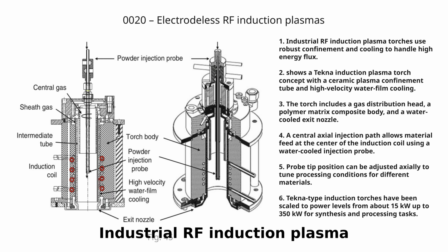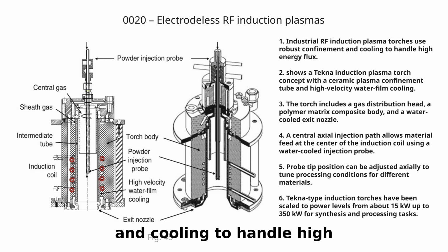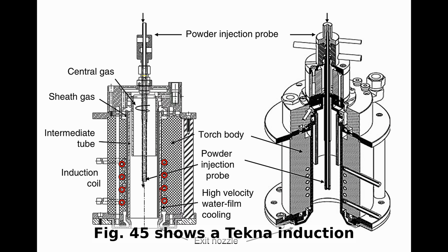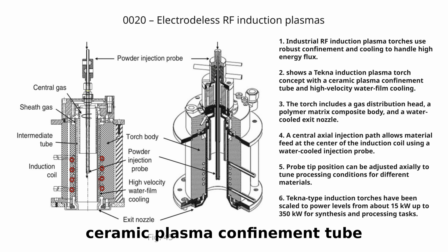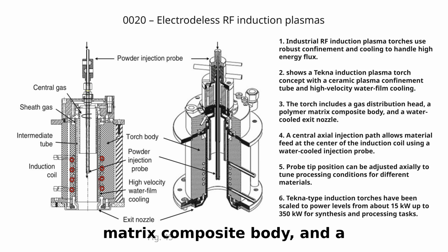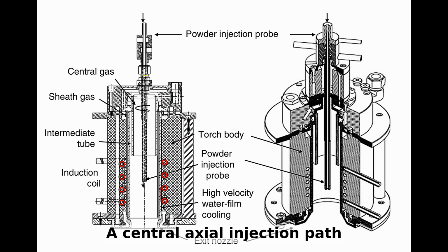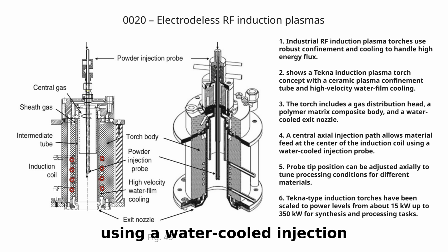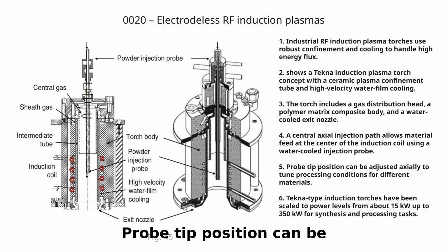Industrial induction plasma torches use robust confinement and cooling to handle high energy flux. Figure 45 shows a Tekna induction plasma torch concept with a ceramic plasma confinement tube and high-velocity water film cooling. The torch includes a gas distribution head, a polymer matrix composite body, and a water-cooled exit nozzle. A central axial injection path allows material feed at the center of the induction coil using a water-cooled injection probe. Probe tip position can be adjusted axially to tune processing conditions for different materials.